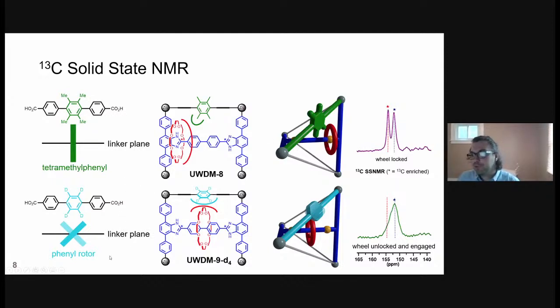Things, of course, are different when we have UWDM9, as we have this less bulky ligand, which is also able to rotate in and out of the linker plane. So we see a single peak at all temperatures corresponding to the unbound recognition site. And so this means that the ring isn't actually binding at either recognition site, and we believe it simply sits about the middle of the axle here. And this is the sterically least congested position, as it's away from these tight corners of the tetrahedral cavity, which are quite sterically demanding when it's binding at this recognition site. As it occupies this position here, it's potentially going to be coming into contact or interacting with this phenyl rotor of the coligand, and we can probe that further with